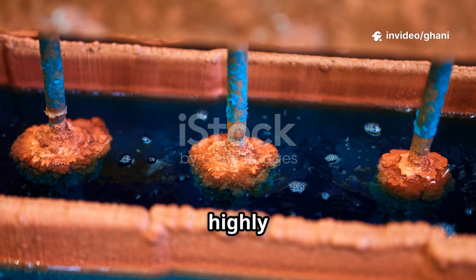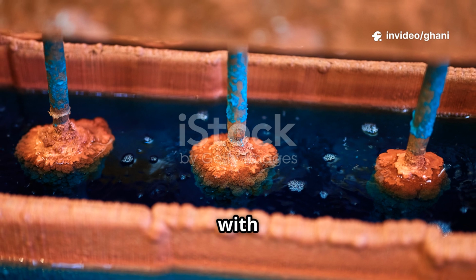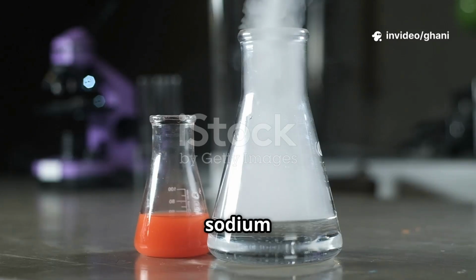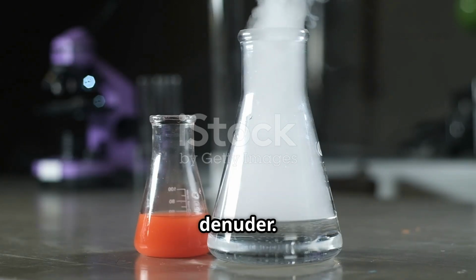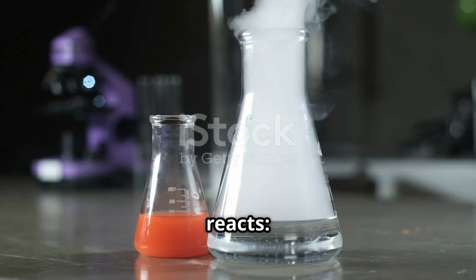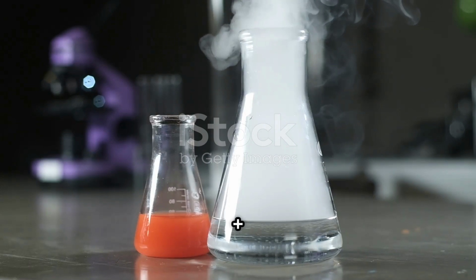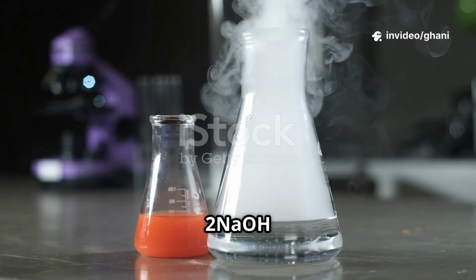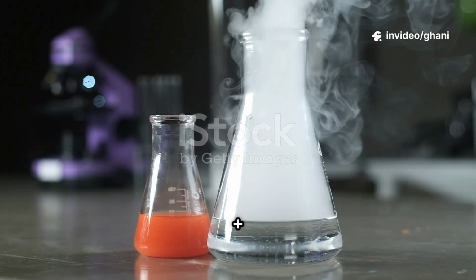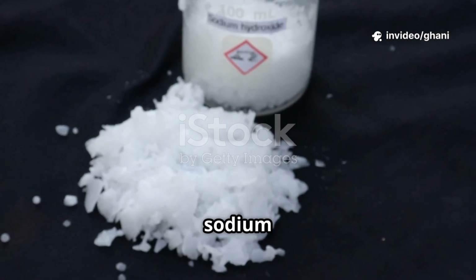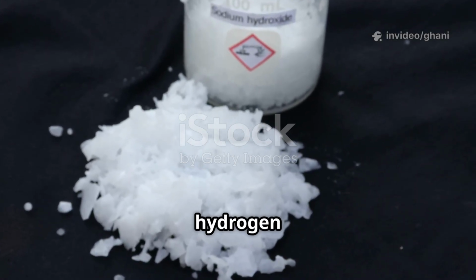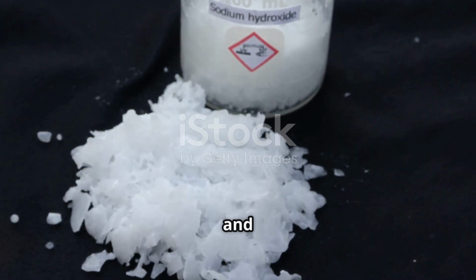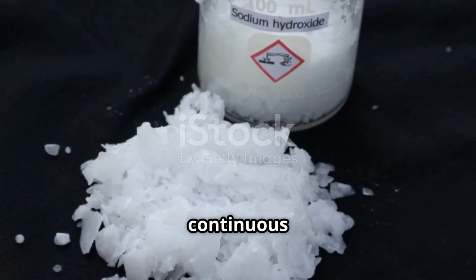But pure sodium is highly reactive. It immediately combines with mercury to form an amalgam. The sodium amalgam is pumped into the denuder. Here it comes into contact with water and reacts: 2NaHg + 2H2O → 2NaOH + H2 + 2Hg. This reaction produces sodium hydroxide in solution and releases hydrogen gas. The mercury is recovered and recycled right back into the cell for continuous production.